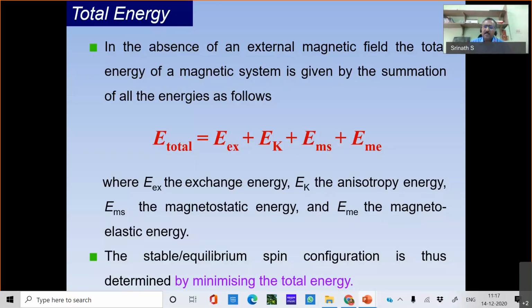But along the face diagonal, you need to apply more field in order to magnetize to the same energy. On the other hand, along the body diagonal, 111 or 1 bar 1 bar 1 bar, it is the hard direction. You need to apply a large field, because the spins don't prefer to orient there. Why? Because of the spin orbit interaction. That is again too many details, so let's not go into that now. Because of this spin orbit interaction, the spins do not prefer to orient along, say, the body diagonal. But I can do it.